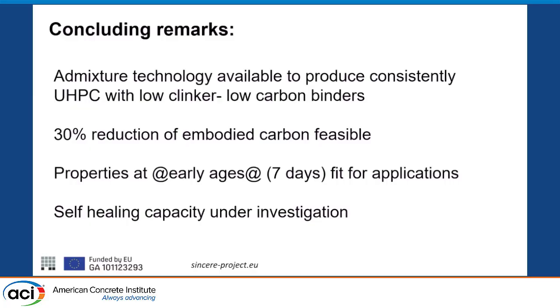So actually, what can we conclude? Obviously, you need to work with admixture technology developers to have the right products in order to get the fresh state performance that you want, to produce the consistency of the material that you like. But we were very happy that we could demonstrate that we could produce UHPC-like materials featuring good compressive strength, but most of all a very significant flexural and toughness performance using low clinker, low carbon binders. We demonstrated that it's feasible to have a 30% reduction of the embodied carbon footprint, and if we keep the mechanical performance and the durability, we can keep the same benefits coming from the UHPC technologies.